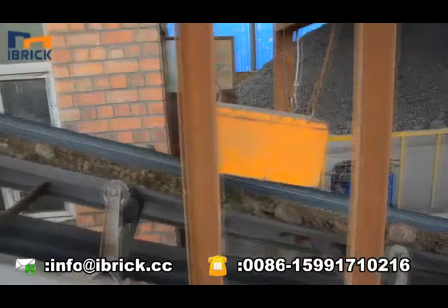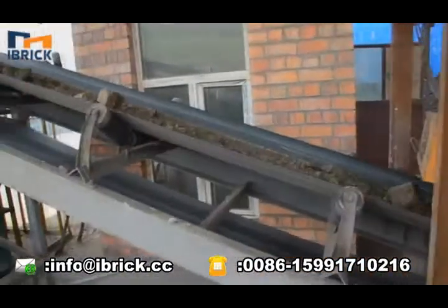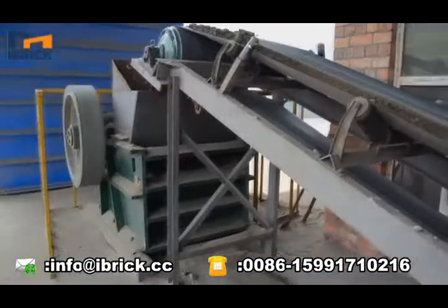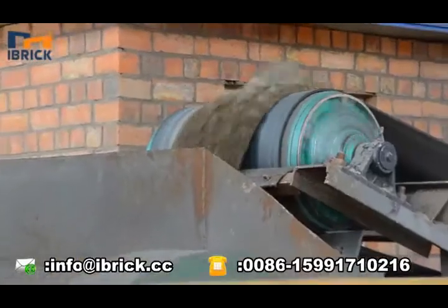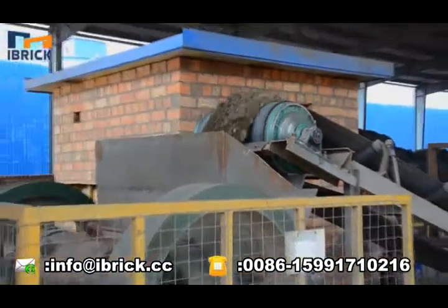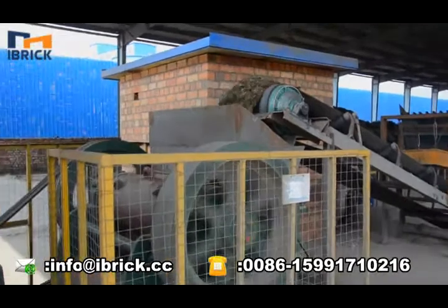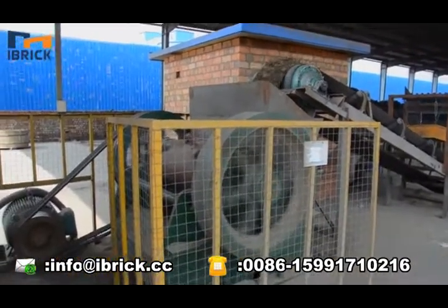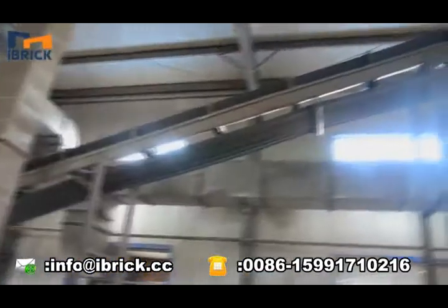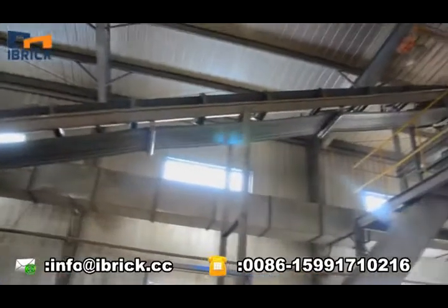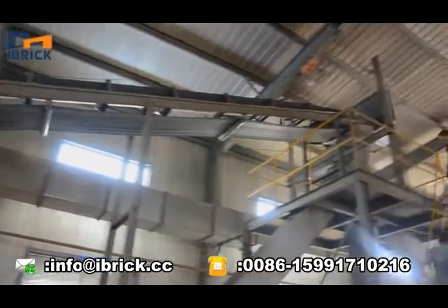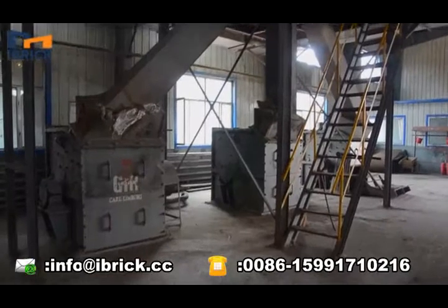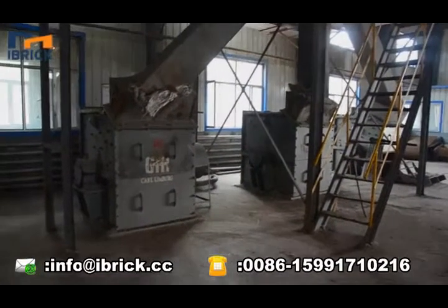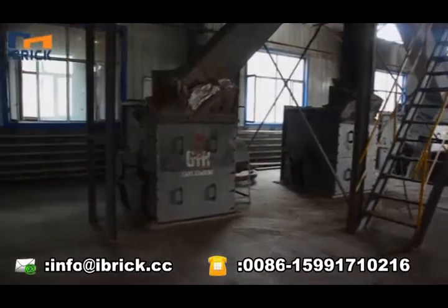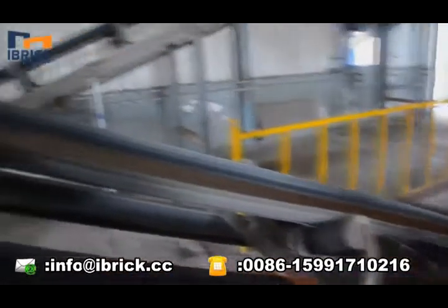Crushed shale will be sent into the hammer crusher together with washery rejects for fine pulverizing, and then screened by a high-frequency electric vibration screen. Oversized materials will be sent back to the hammer crusher to be crushed further. Undersized material will be sent into the double-shaft mixer. Water is added and mixed uniformly here. The moisture content of the mixture materials is 13-14%.